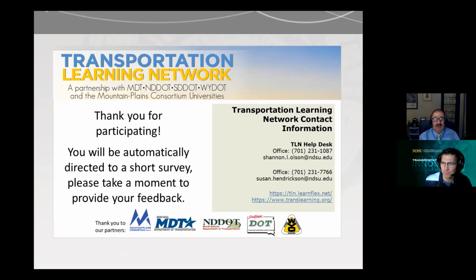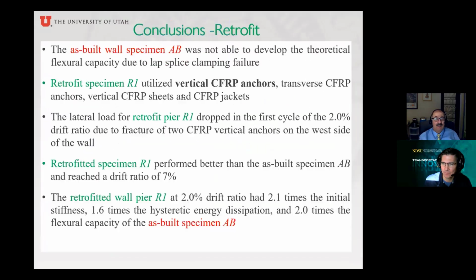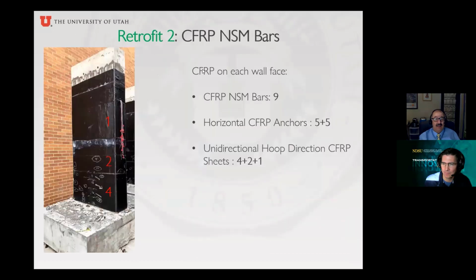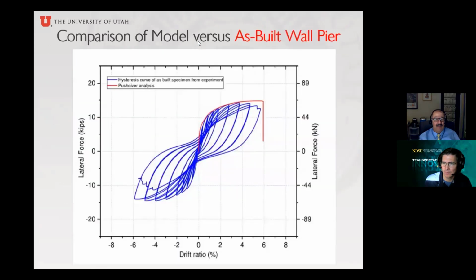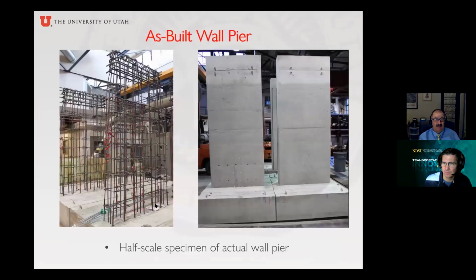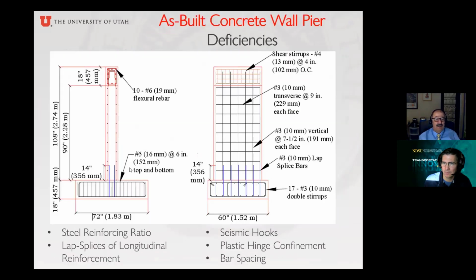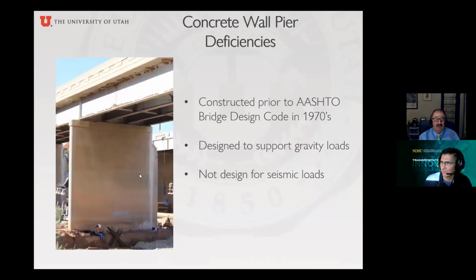for your area, if you have bridges that look like this, typically they are not well designed if they're about the age of the ones that I showed, because they have this problem down here at the splice. This lap splice is very deficient. And in fact, I know for a fact UDOT is tearing down these wall piers. This is a picture near St. George, Utah. And the reason they're doing that is not because of the seismic. I think the seismic is a secondary concern, is because they're widening the bridges. So when they widen this bridge, actually, they didn't use wall piers. They actually use bridge bents. They use 3-column or 4-column bents with a cap beam.